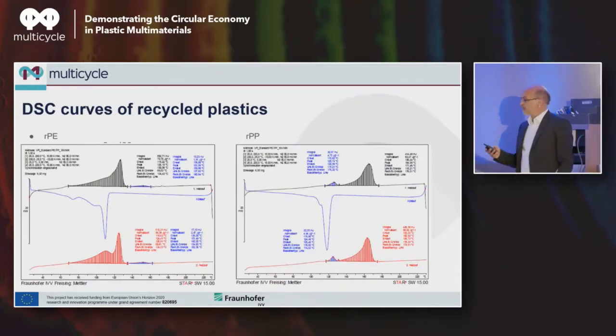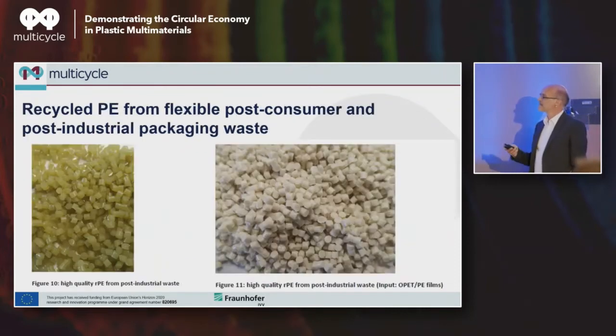Let's talk about some of the qualities. That's one too much. Please, one back. Just to give you a few impressions. This is the recycled polyethylene from post-industrial waste, and it doesn't look too good, honestly. It is still a bit green colored, but you see it looks quite transparent. And if you look into the films, we have many films here, if you have them as a single film later on, you don't see that color anymore.